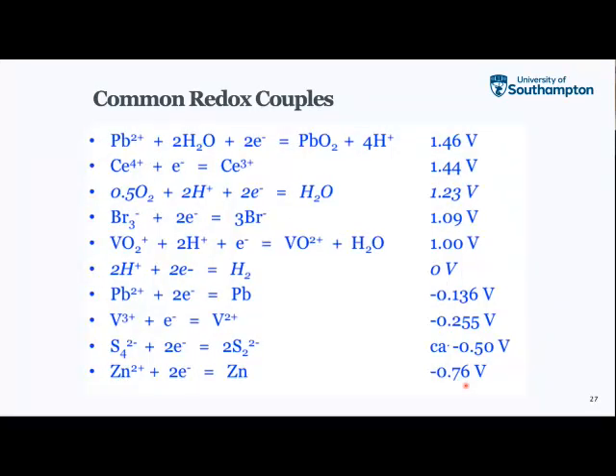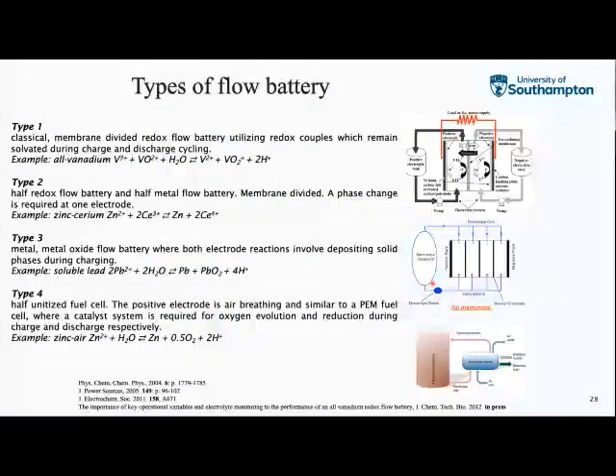As with conventional batteries, there's a number of different flavours and varieties of flow battery and a number of common redox couples. Again, the idea being trying to pick couples that have a reasonable voltage potential to have a good voltage per cell. We've sort of mentioned some of the different types. There tends to be four different varieties, shall we say. So one example is the all vanadium, and as I said, the active species stays solvated at all states of charge and discharge, and you're shuttling between V4 and V5 on one side, and V2 and V3 on the other. V4 and V5 and V2 and V3.